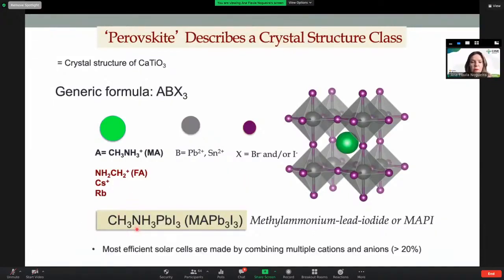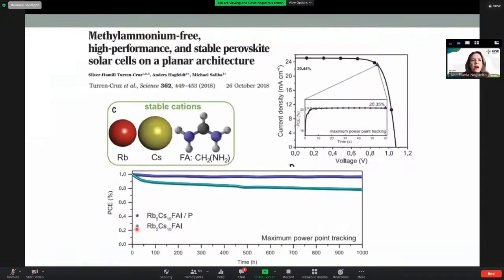However, the most efficient solar cells are made by combining multiple cations and anions, with efficiency then higher than 20%. This is an old example from my colleague Saliba, when he showed in this paper in Science, for instance, efficiency higher than 20% when they mixed in the A site the cations formamidinium, cesium, and rubidium. So we have these three cations in the A site, and we have here not only an increase in efficiency, but also in stability.